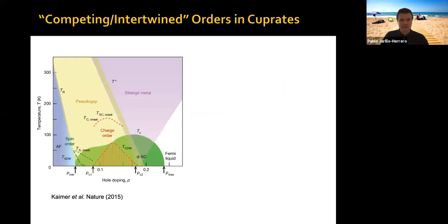This term, competing, and sometimes it's called intertwined orders, comes mostly from studies of the cuprates. This is a phase diagram of the cuprates, temperature versus hole doping. The green part is the superconducting dome. This is, of course, a theoretical map. And you can see that it's not a single superconducting dome; you have this sort of double dome, this camelback superconducting dome. In particular, near this 1/8 doping, 12.5%, there is this anomaly, this sort of kink in Tc.